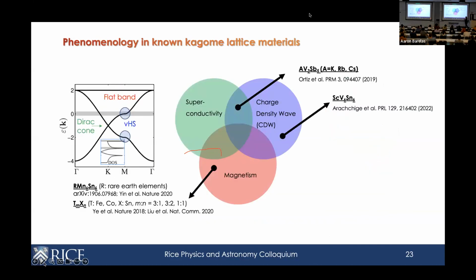So actually, there are many Kagome lattice materials people have looked at in recent years, and from this very simple, maybe half naive correlation of these electronic structure features and their material property, it's not hard to see that the materials, don't worry about what they are, but just look at this. They can be grouped into 2 parts, right? You have materials that only exhibit charge density wave but no magnetism, or you have materials that only live in the magnetic phase but no CDW.